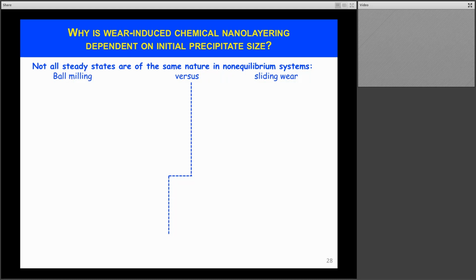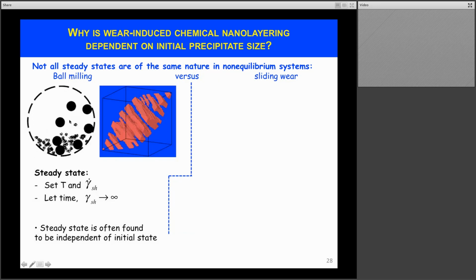One point that I think is important to appreciate is that these non-equilibrium systems can reach different steady states, but the steady states are not necessarily all the same. So doing ball milling, on the left-hand side, what happens is that we prepare the system by setting the temperature and the plastic strain rate, and we let it evolve for an infinite amount of time, or for an infinite amount of strain, and it reaches a steady state, which may be this layered structure. And often what is found, and this is the case both here in the simulation and the experiments, is that the steady state is independent of the initial state.